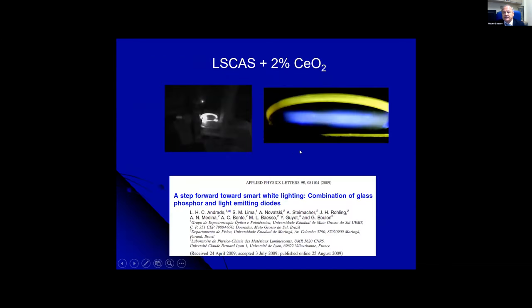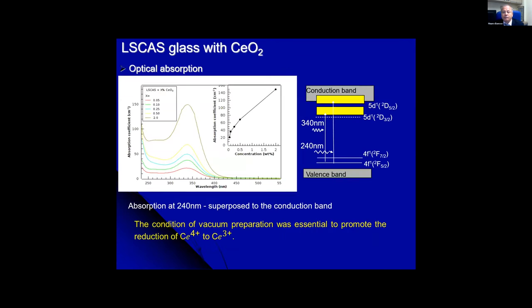Well, the first work on this glass for white lighting was in this paper in 2009, where by accident we were investigating the cerium in the glass, just to try to understand the structure of the glass, and we observed white light emission from the glass. Then we started to investigate all the spectroscopic characteristics of the glass to understand what was going on. The first thing was that the way we produce the glass under vacuum atmosphere, we induce cerium 3+, because usually in oxide glass in room atmosphere, you will get cerium 4+. Cerium 4+ is something transparent. And this way we got cerium 3+, and then we got the absorption bands.